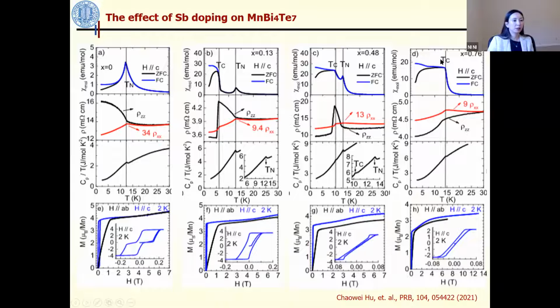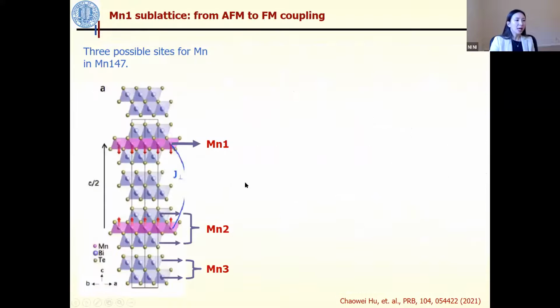Okay, so here you can see the summary of our data. Besides this additional ferromagnetic-like transition at the TC, if you look at the MH data, we found that the saturation moment with doping is actually decreasing. I will say the moment around 7 Tesla decreases from 4.4 μB per manganese down to 3.2 μB per manganese here. So what happened here? Why does the antimony doping introduce this rich and complex magnetic evolution in the 147 compound?